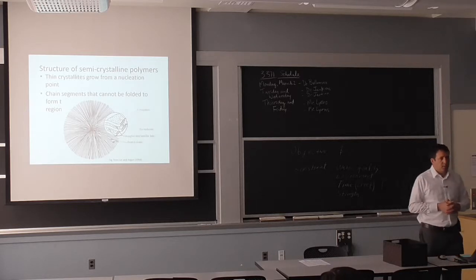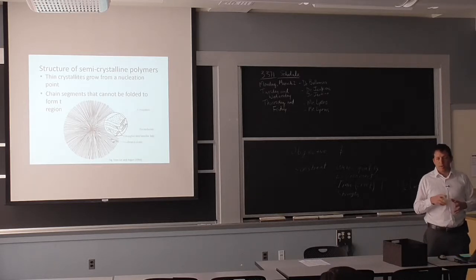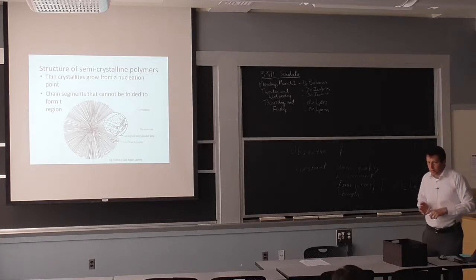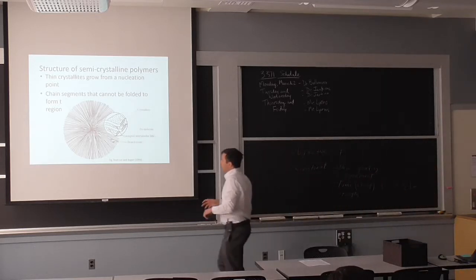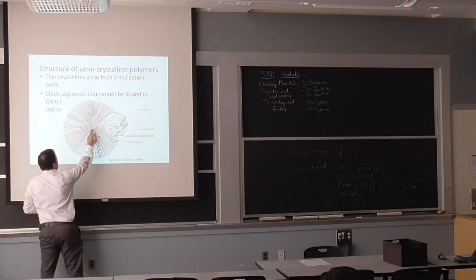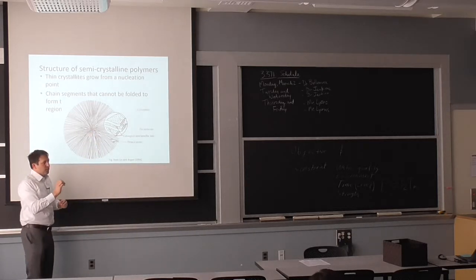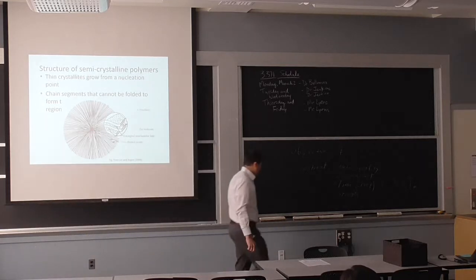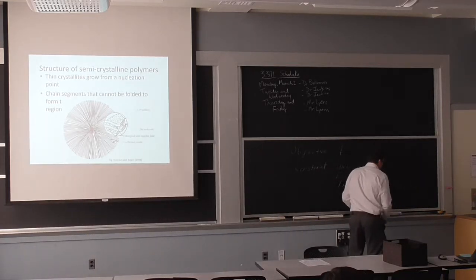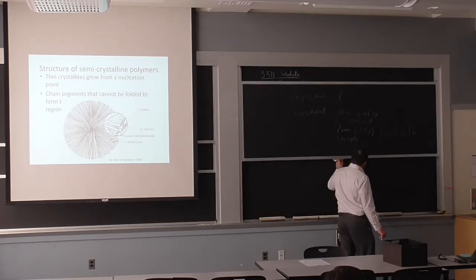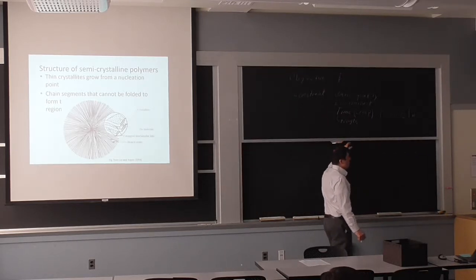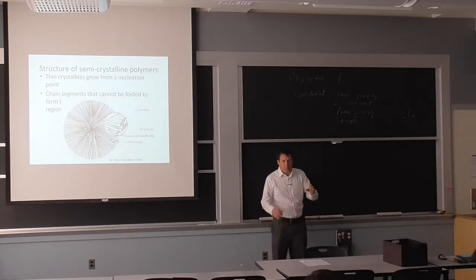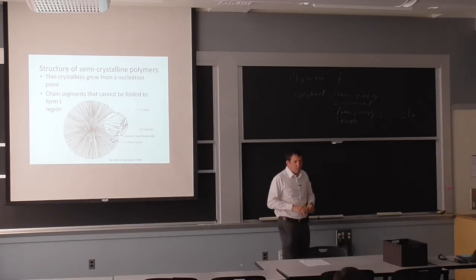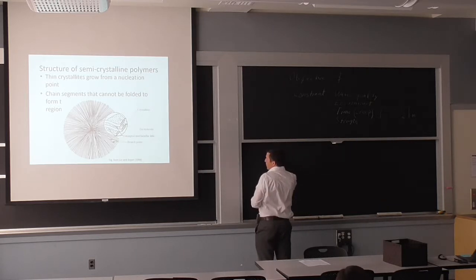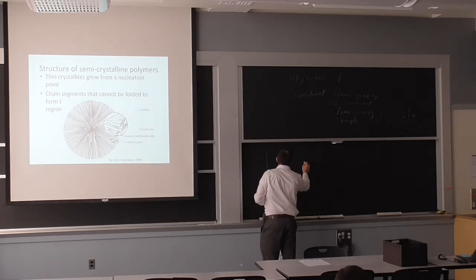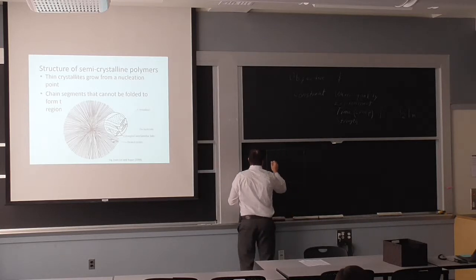If you cast the polymer, most of the times, polyethylene, polycarbonate, and even PVC, nylon is a good example, so polyamide, you'll start forming a crystal at a certain spot in the volume. So what happens in this type of materials is, we haven't talked about metal casting, but metals will tend to form grains from the surface of the mold. But here with the polymer, partially because it's a lower temperature, if I have a certain volume here, I will typically, and there's no specific